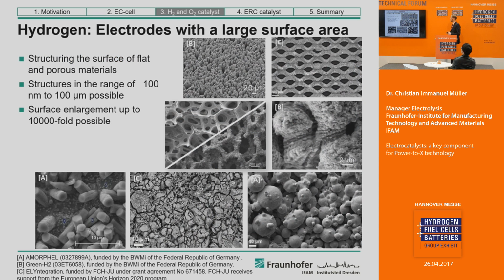So there are two approaches to develop very good electrodes. The first one is to increase your intrinsic activity. The second one is to enlarge your surface area. The second one is much easier and gives you better results. So what we can do, we can enlarge the surface up to a factor of 10,000.